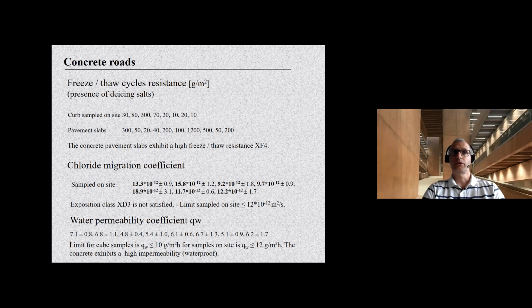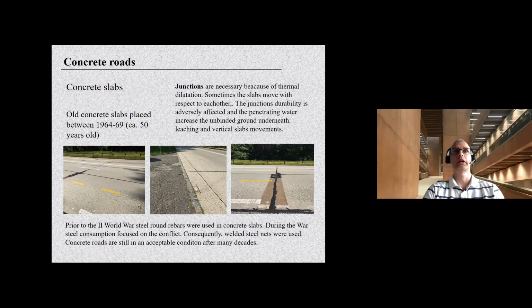If we also have a look at the water permeability coefficient, you can see that the values we measured are pretty much below 10 gram per square meter per hour. And this is an indication that the concrete exhibits a high waterproofing quality.